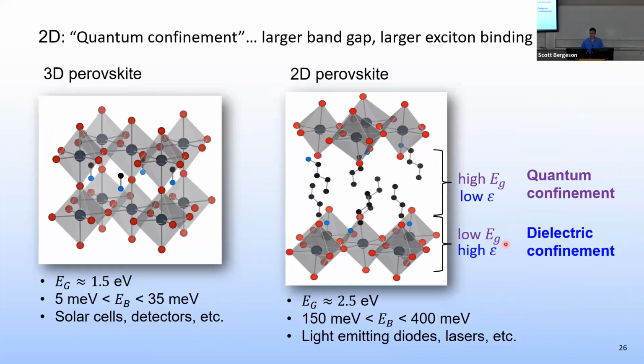The sheets here cause quantum confinement, just like those nanoparticles that I was talking about earlier, where you have confinement effects that affect the energies. In fact, they bump up the band gap energies, and they also bump up the binding energies because the electrons and holes are forced into these sheets. They're closer to each other, they bind to each other more strongly. There are also important dielectric effects that happen in these materials, which probably in the interest of time, I won't get into at all. But there's a dielectric mismatch between the molecules and the metal halide things.